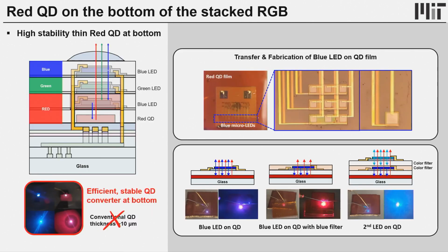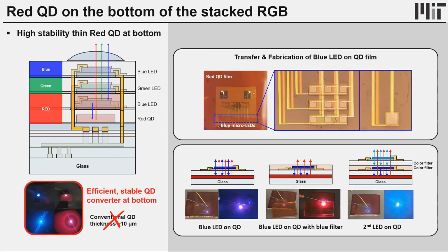Also, by working with Professor Moungi Bawendi, we try to add his red quantum dots on the bottom of our LED stacks, on the bottom, not in the middle, because typically you need pretty thick red quantum dots to re-emit the light. Right? So if it's thick and if it goes in the middle, then it's already very tall. But we are working together to find a way to put it down here, ultra thin, so then you can also still use blue InGaN LEDs as a light source. Then we can do the quantum dot. That is a part of the topic that we are working on together.